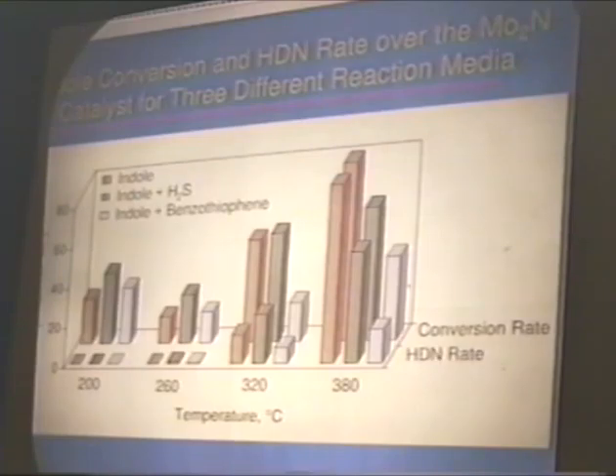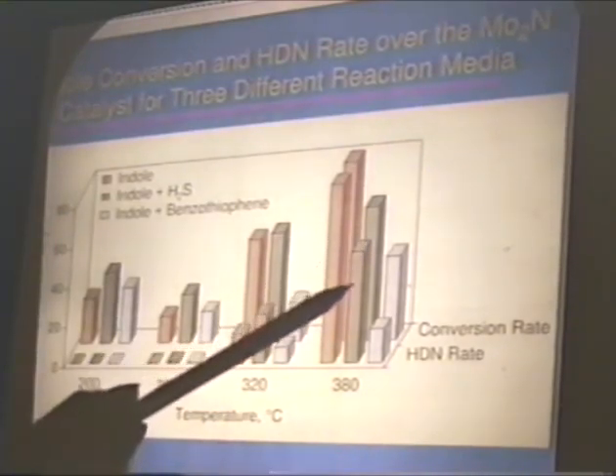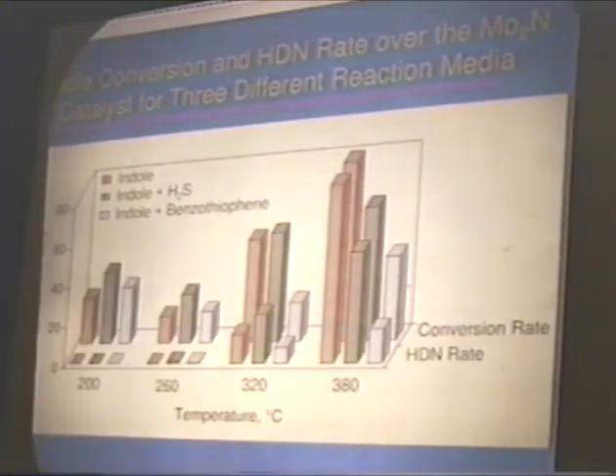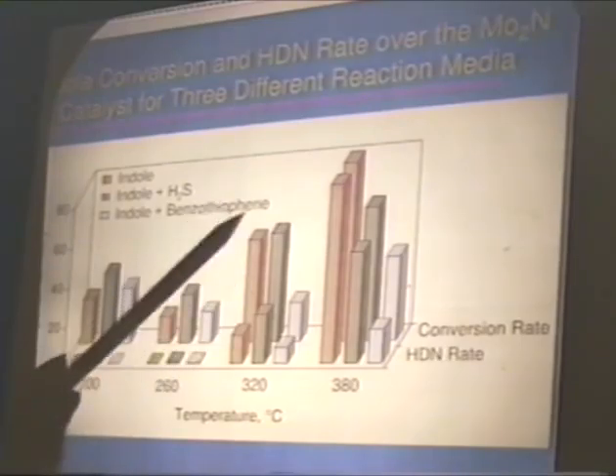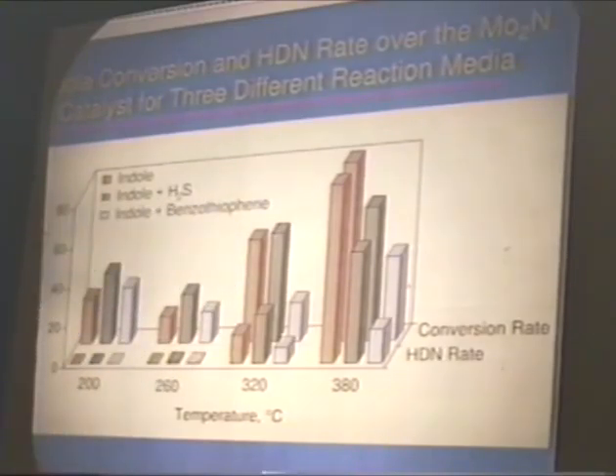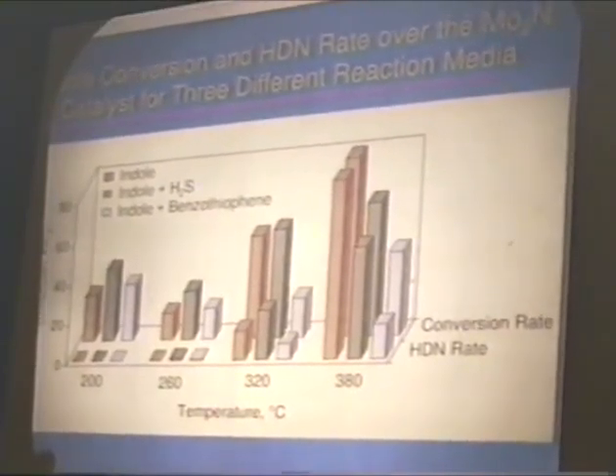Another interesting feature to note is that when we have sulfur compounds present in the system, especially if we look at this high temperature, we see a significant inhibition effect. As you can see, both the conversion rate and the HDN rate are lower. HDN rate seems to be more affected, and if we compare H2S versus benzothiophene, we see a much more severe inhibition effect when we have benzothiophene present.